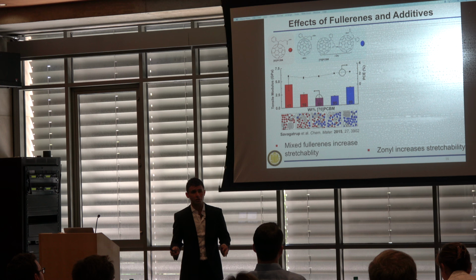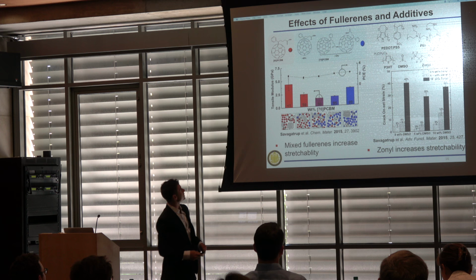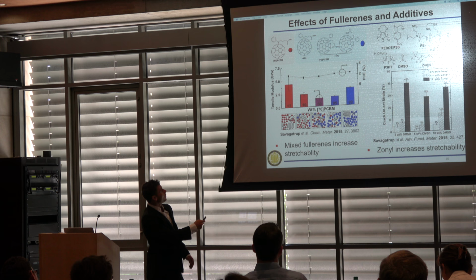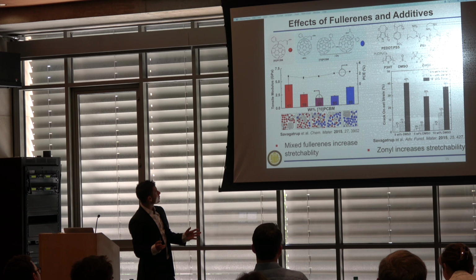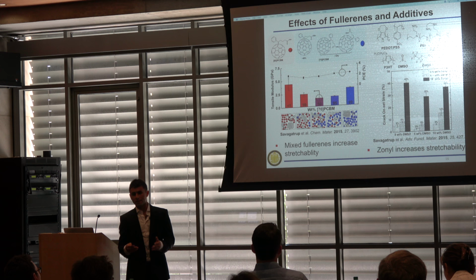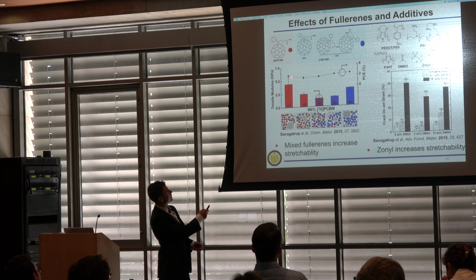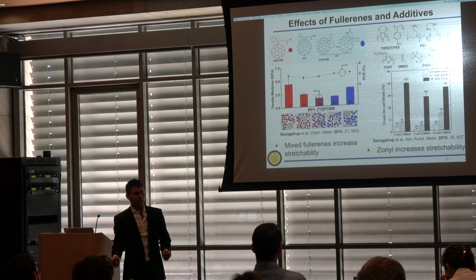So in two more studies, we see the choice of fullerene affects the mechanical properties too. When fullerenes are made, you get a mix of C70 and C60 Buckminster fullerenes, and an intense amount of energy is used to purify them and separate them from each other. But if you do this, you don't actually get much increase in your efficiency. So here we see, even if you have pure or mixes, you get roughly the same power conversion efficiency.